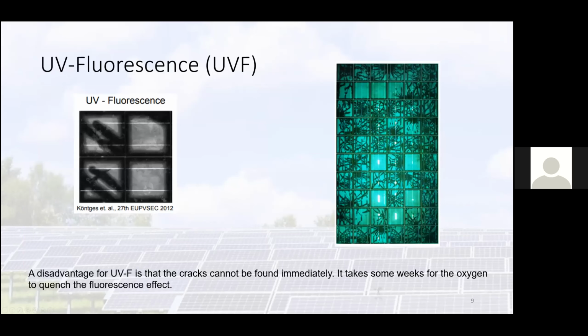UV fluorescence is a method which uses UV cameras, and you can see the defects which happen because of long-term exposure of solar panels to sunlight. So you can see, by illuminating with a UV source, or using a UV camera with a filter, how these elements look under UV light, and you can see the defects which accumulate during the use of the elements.